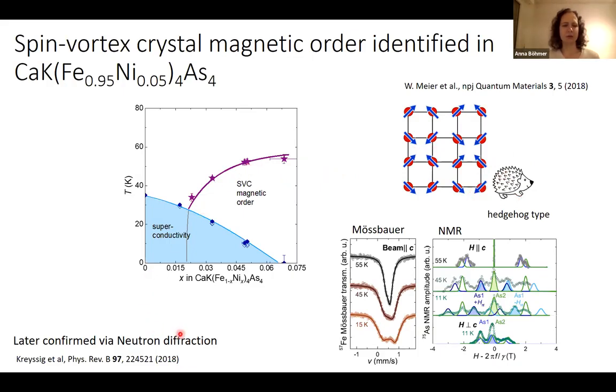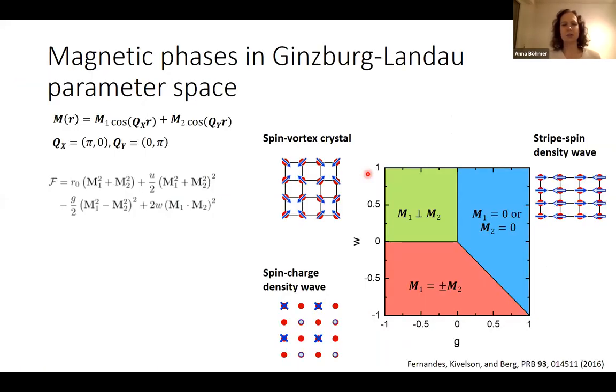This was also later confirmed by neutron diffraction. So now we have a variety of magnetic orders in the iron-based compounds, and to give an overview and some systematics, let's go to some theoretical description. To describe this order, and that was done long ago, we can use two spin density waves. One with two equivalent wave vectors and two different order parameters, M1 and M2. To recover the stripe phase, one of these order parameters is set to 0, and then we get our stripes.